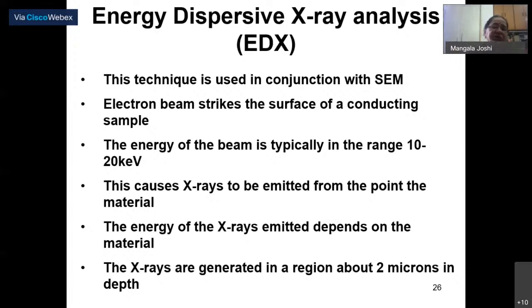In SEM, the sample preparation is very important, because our fibers and polymers are non-conducting in nature. So we have to make them conducting by giving a very thin coating of gold or any other material, which makes the surface conducting. But it has to be a very thin coating so that it doesn't disturb the topography of the sample. The energy of the beam, which is typically in the range of 10 to 20 kilovolts, causes X-rays to be emitted, as I have just shown in my previous slide, from the material. And the energy of the X-rays emitted depends on the material. The X-rays are generated in a region about 2 microns deep.